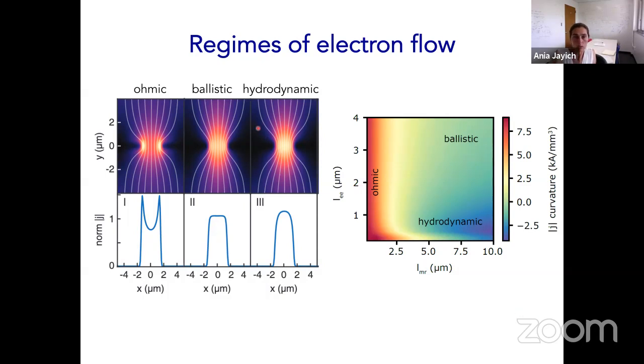Okay, so we picked the slit geometry because it has distinctive features for electrons in these three different transport regimes of ohmic, ballistic, and hydrodynamic. In the ohmic regime, using Andy Lucas's code to plot the spatial current density, one expects to see what we call ears: increases in current right near the edges of the device. One can almost think of this as a lightning rod effect, where you have an increased electric field near these edges, and that gives you increased current there. In the ballistic regime, electrons will just bounce through this device. They don't feel each other at all, and you expect a flat profile in the current across the constriction. In the hydrodynamic regime, importantly, electrons do feel each other, and through their interactions with each other, they feel the edges of the device, and they exhibit this rounded current profile through the device.